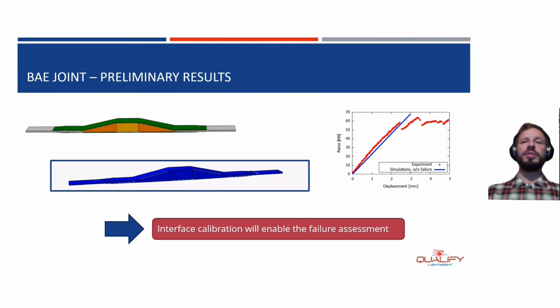A similar approach can also be taken for the BAE joint. As an example, I want to show here some preliminary results we got for the joint. As you can see here on the right-hand side, the force displacement curve, again, I chose 2 points here with the relative displacement, and the results of the simulations match the experiments relatively well.